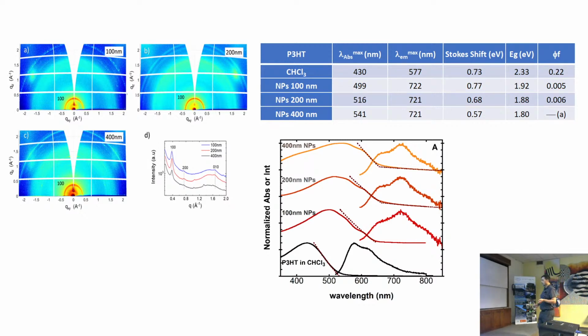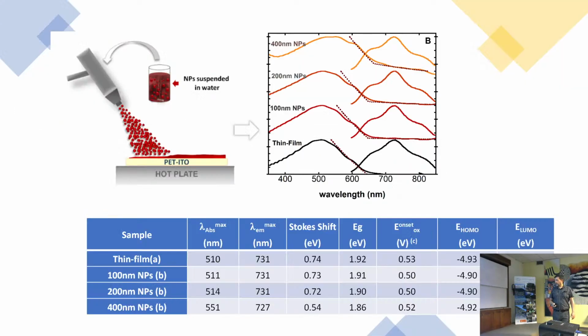This has an impact because the fluorescent intensity decreases a lot, so the quantum yields become extremely low, and in some cases the fluorescence disappears completely. And the Stokes shift also increases, not so much, because what changes a lot is the band gap. So the band gap becomes much smaller. Okay, so we characterize the nanoparticles, then we make the deposition to characterize the thin films. And now, when you do the thin film from the polymer in chloroform, it matches very well the spectrum of the nanoparticles that remain fairly the same as in the suspension.